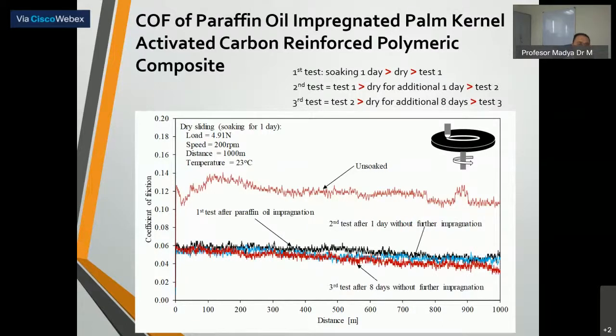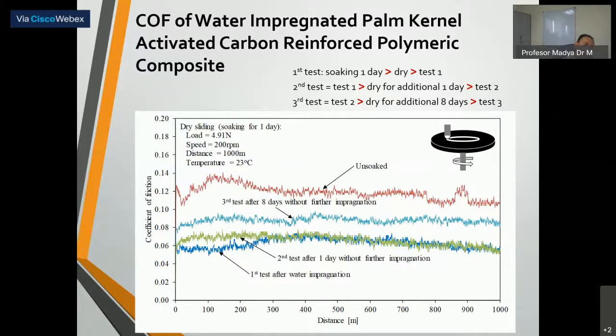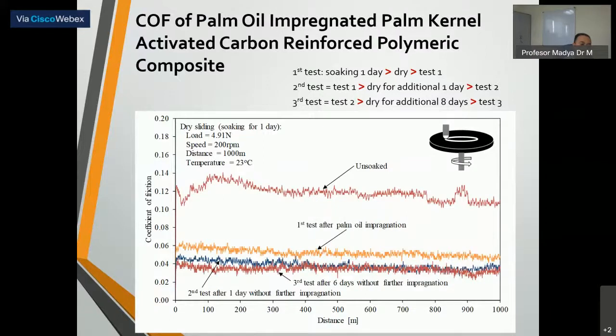Okay, this is the paraffin oil. We can see that even after test 3, which is after we dry for an additional 8 days, the coefficient of friction is still similar, about 0.06. In water, it is still about 0.06, but after the test we can see that the coefficient of friction increases to about 0.08. Okay, and then this is impregnation with the palm oil. We can see that with the palm oil, the coefficient of friction is lower than with paraffin, about 0.04 for the palm oil, but with paraffin it is 0.06. So this is the advantage of the palm oil.